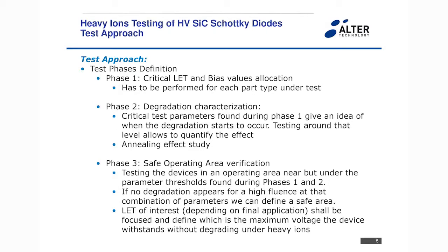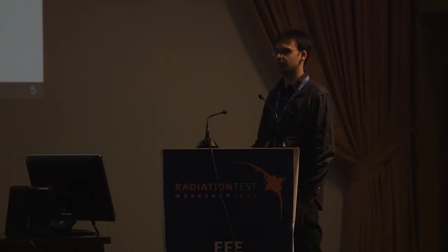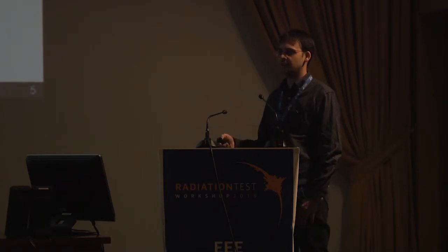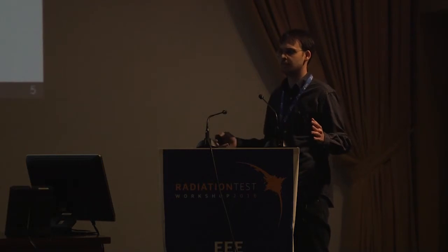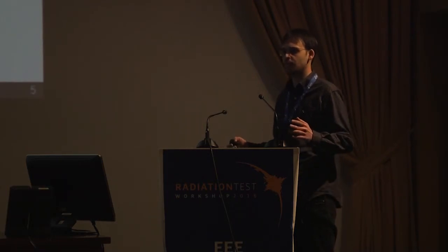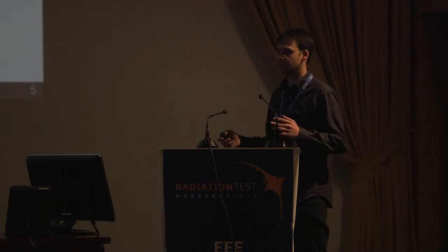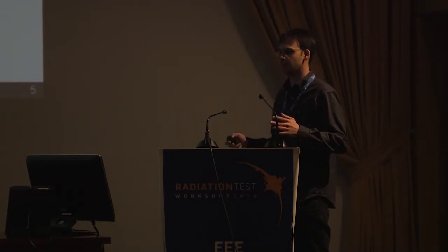This leads to a several-phase approach, and we have defined three phases. Phase one is the critical LET and bias value allocation. We perform this phase on the different part types, performing heavy ion runs at each LET with different voltage steps, but very wide voltage steps, because we didn't know where the devices were going to fail. So this is only allocating the problem.